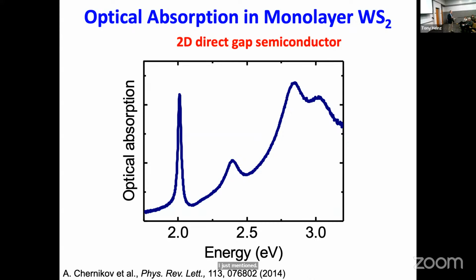But for those of you who might have taken a course in solid state physics and optical properties, there's sort of a paradigmatic way that you describe to first order what the optical spectrum should look like, and that is you count states. So you look at the joint density of states, and famously, if you have a parabolic band in 2 dimensions, you might know that you get a step function for the joint density of states. So in the simplest picture, this red line is what the optical absorption spectrum should look like. You have to get to the band edge, and then you have a constant absorption.